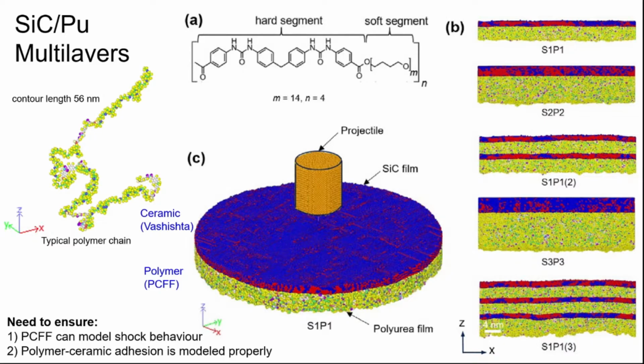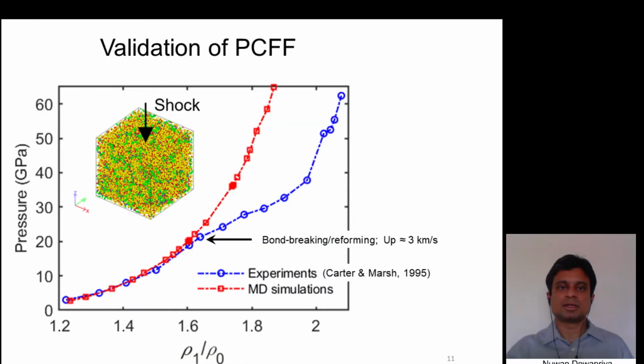The other important thing is that PCFF and the Vashishta potential are completely independent, and we need to make sure that the interaction between these two materials is modeled properly. In order to validate the potential, we computed the shock Hugoniot of the polymers using the PCFF and compared them with the available experimental data.